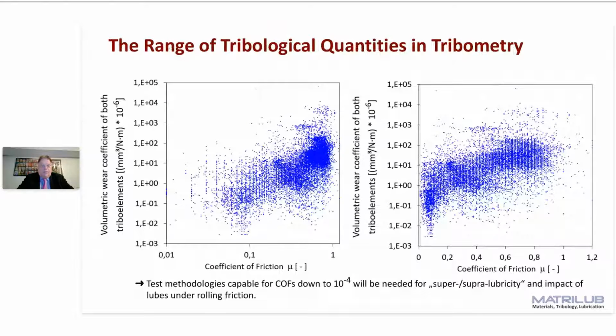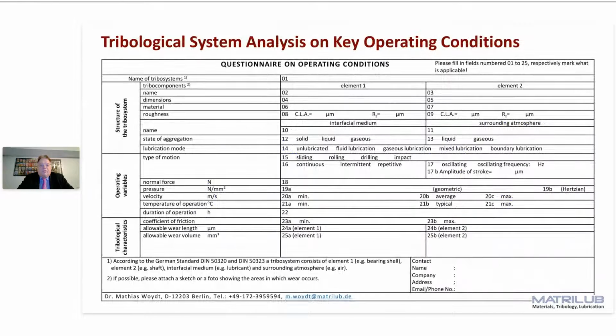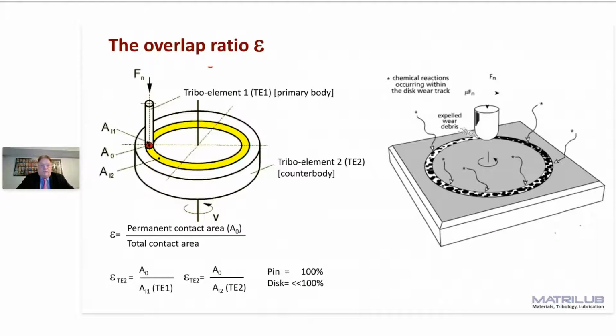So if we go back now to these diagrams, you see a wide range of coefficients of friction and a wide range of wear rates. So the question is not whether a test result is good or bad anywhere, but whether the test result meets your tribological system analysis. It means if you have a wear rate which is allowable, all test results should be below. So by selecting results, it's not the question whether you are good or bad. The only question is, do you meet or do you not meet what you have analyzed by this questionnaire.